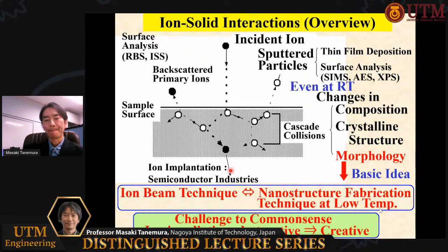Incident ions induce the ejection of the surface component atoms. This process is called sputtering. These sputter-ejected particles are used for thin film deposition and surface analysis. At the surface, cascade collisions occur, and in this cascade collision process, surface composition changes, crystalline structure changes, and morphology changes. Such a morphological change occurs even at room temperature.